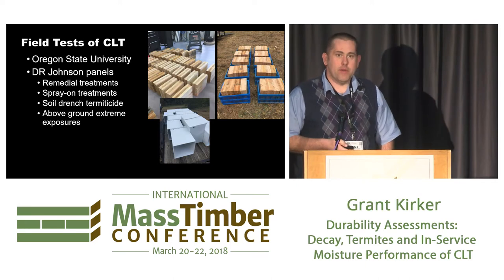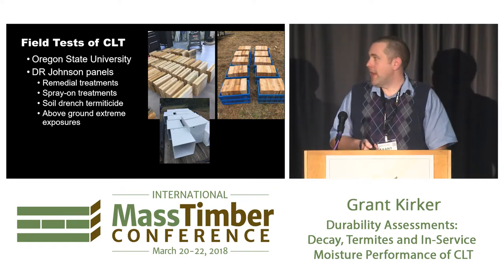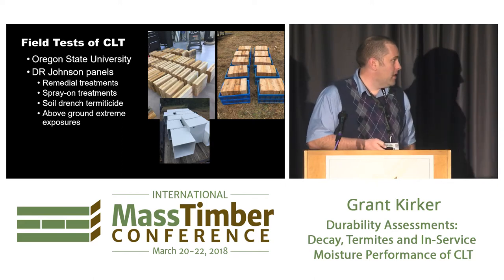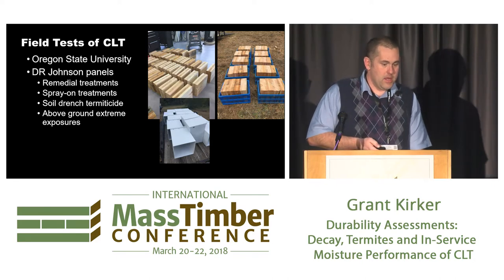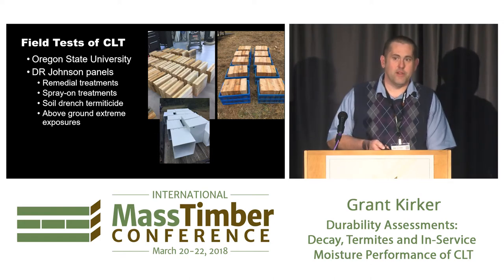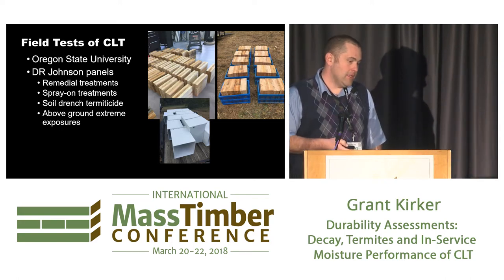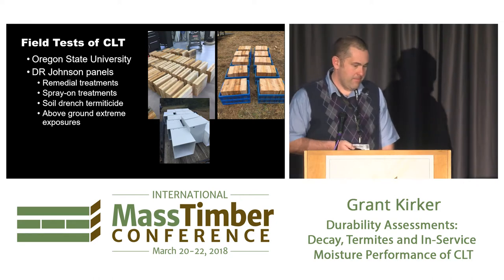So the fourth project that we have: last year we got some panels donated from DR Johnson, and these are actually, I think, window and door cutouts that were sent to us. Jeff was a big help in getting this done. And this is kind of our first stab at field testing of CLT. We put these out in our field test sites at the Harrison Experimental Forest, which is in Saucier, Mississippi. It's a hazard zone 5, which is considered severe by the AWPA hazard zone map.